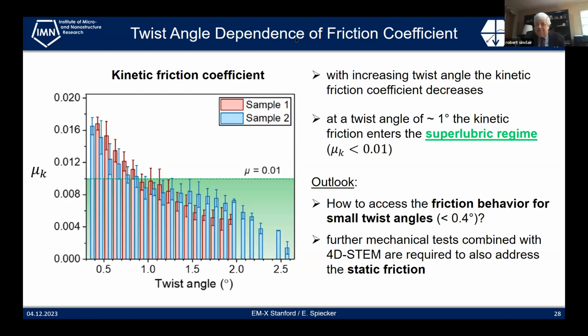You mentioned the sample was difficult to obtain or difficult to find, and so the sample preparation sounds pretty critical as well. Yeah, this is definitely the case, and Show actually used also sometimes, if we see this configuration, the electron beam to cut other parts of the samples to set this part free for the experiment. But of course you have only one shot for each configuration, and you have to take all the data, and you don't know the stick-slip motion in advance, whether there are many small steps of sliding or a big step of sliding. So this makes the experiment extremely challenging.